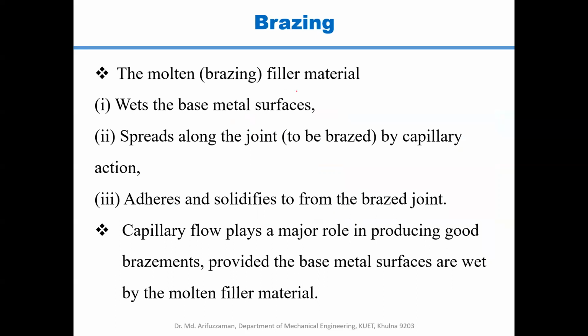So for brazing, the molten filler material actually has three functions. One is to wet the base metal surfaces. That means the base metal that is being joined first needs to be wet so that capillary action can take place, and it spreads along the joint by capillary action. When capillary action is activated, the molten metal flows through the small space between the workpieces, and upon solidification produces a very airtight joint, with no effect on the base metal. The third function is that it adheres and solidifies to form the brazed joint. In brazing, capillary action plays a very important role in producing a good brazement, provided the base metal surfaces are wet by the molten filler material.